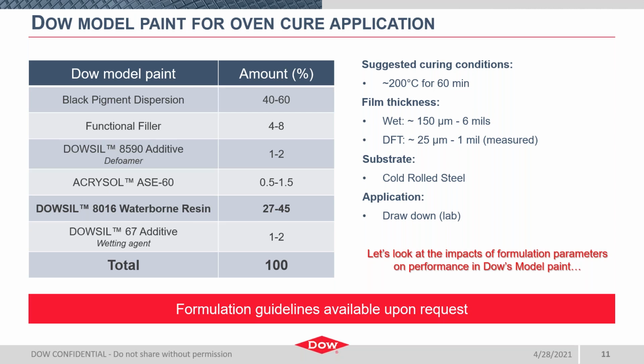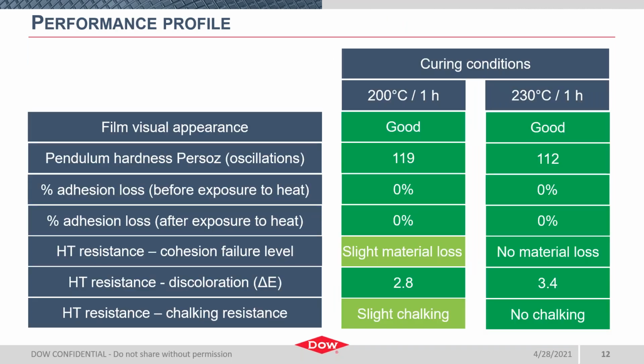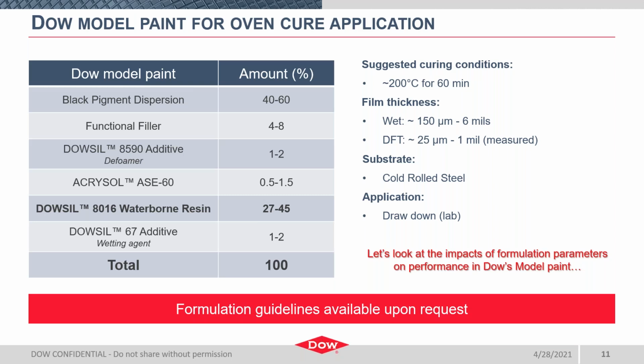While we are working on a formulation for room temperature cure, we recommend this formulation outlined here be cured above 180 C for an hour. So very consistent with the mature solvent-based silicone resins supplied. And finally, film thickness for all pictures I'll show was kept consistent and measured at approximately 1 mil dry. So for the rest of the presentation, I'm going to share the performance profile of 8016 through data and pictures according to this formulation range. And this is going to become the framework for recommended starting point formulations. I guess the only caveat I'll mention is that our acrylic modified formulations towards the end will have a bit of a different formulation set, but I'll be sure to call that out.